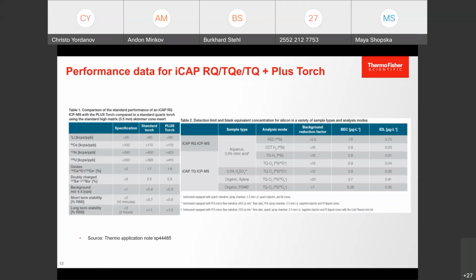As a takeaway, we could say on optical ICP, this ceramic torch does not have benefits except for the fact that it never breaks, but also no negative. But on ICP MS, this special ceramic torch has only benefits. It should not break. Up to now, we haven't seen any customer breaking this torch, or mineralizing or aging, and it's granting a better sensitivity. So it's a win-win torch, and we assume that for a little price markup, most of our customers in the future will go for ICP MS with our new Plus torch.